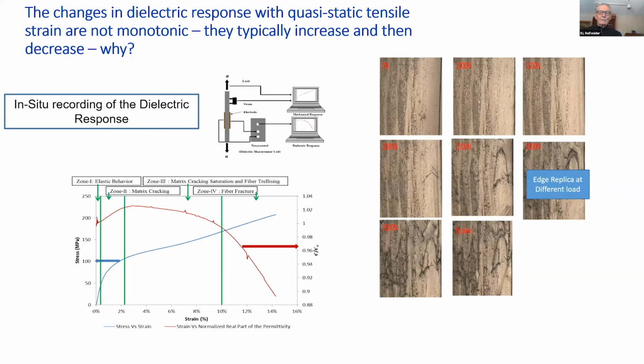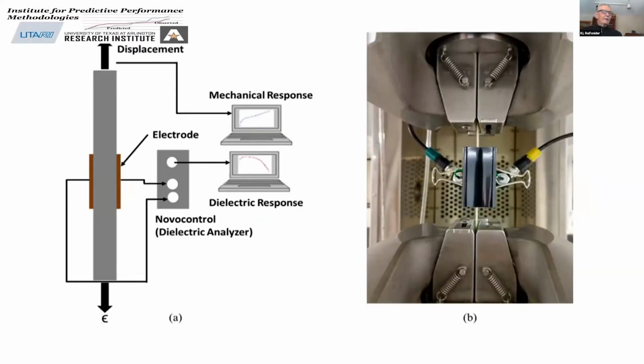Here is the experimental setup, and you can see that we have two plates on either side of the thickness of a specimen. We're placing an oscillating voltage across it. The experiment itself is shown on the right. This happens to be a glass epoxy specimen, and we're oscillating the voltage through it and measuring the cyclic response.